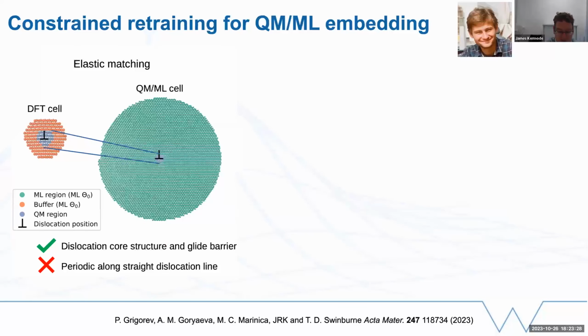And this is work done by a former postdoc at Warwick, Petr Grigorev, who's now in Marseille at the CINaM Research Institute. And the idea here is to take the setup that I've shown you so far, so a two-dimensional sort of cylindrical setup. Now we're interested in a dislocation rather than a crack, so a different kind of line defect in a material. And with a QMMM type approach, we can correctly recover the core structure in the region of the dislocation. We can correctly describe dislocation glide, the motion of the dislocation in a glide direction. But we're limited in that this is a narrow periodic simulation, so the dislocation is forced to be straight. Whereas in reality, we know that dislocations move through the formation and growth of kinks. So how could we lift that limitation?